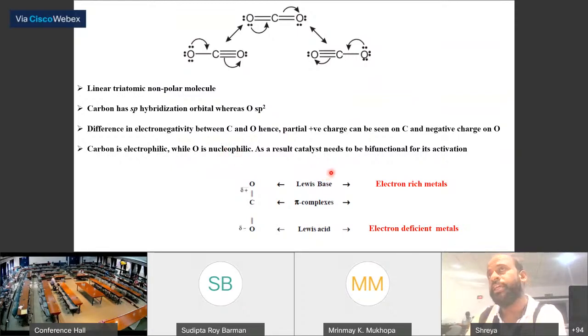Because of this nature, when you design the catalyst, you have to have a mixture of electron-rich and electron-deficient metal. And this will change the mechanistic pathway, depending on what desired product you are looking for. Nickel is very famous as a metal for methane formation, but when it forms nickel 3 indium, it is converting to methanol.